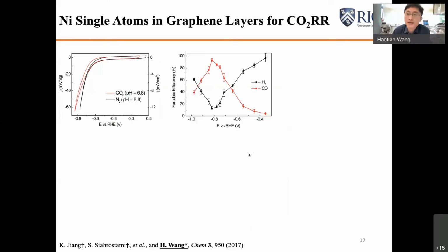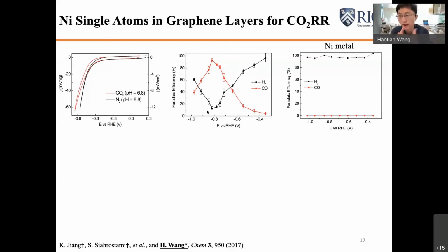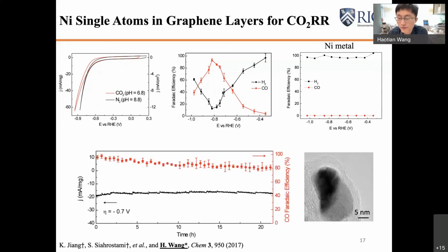So we tested our sample. And as a result, a very promising result is, as you can see, with more and more negative potentials applied, we do see the CO selectivity slowly jump to more than 90%, and the hydrogen evolution gradually suppressed to less than 10%. So by tuning the structure of a nickel catalyst from a nanoparticle to a single atomic site, we can completely flip over the preferred reaction pathway. As you can see, from these nickel nanoparticles, they get 100% hydrogen, but with the nickel single atoms, we get more than 90% CO out of CO2 reduction, and the stability is also very promising.